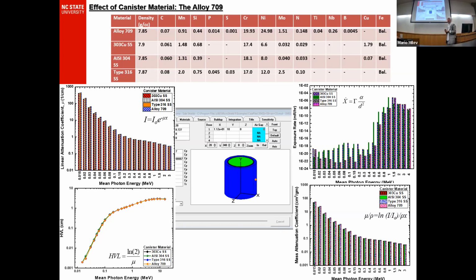Also, we look at the half value layer, which is the thickness at which radiation is reduced by half. It equals ln2 over mu. The lower the half value layer, the better the shielding effectiveness, and alloy 709 exhibited the lowest half value layer among other stainless steels.